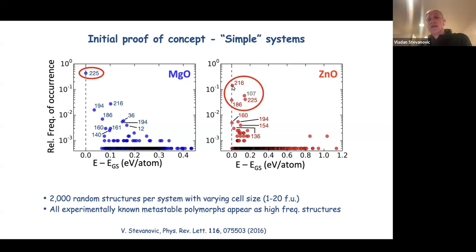So out of the 4 highly occurring ones, the 3 that are in red, which are dynamically stable, are the ground state wurtzite, the zinc blende structure, and the rock salt, the 3 known polymorphs of zinc oxide. So this again is pretty much a one-to-one correspondence with the experimental facts that are known about zinc oxide, another system that has been grown many times with many techniques. So it's not that we are missing something experimentally.